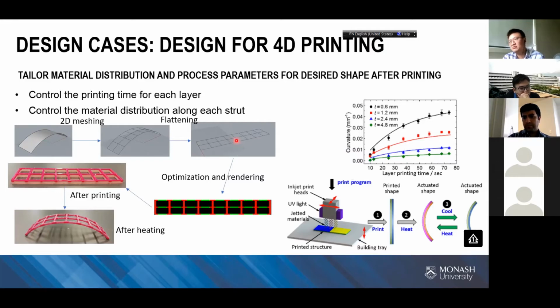Actually, the reason it can change shape is that we found that during the printing process, the residual stress will be stored in one of the materials called Tango. After printing, we used another material called Vero to lock the residual stress. If we put it in hot water, and the water temperature is larger than the glass transition temperature of the rigid Vero, the Vero will become soft and the residual stress will release. According to the different amounts of digital material we used, we can achieve different shape deformations.